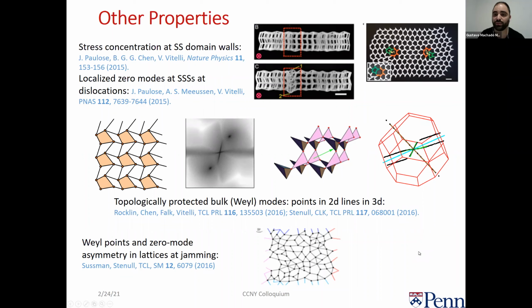Okay, so even though it's not fully, you still have some wiggle because it's not 6 nearest neighbors. Unless you've chosen some particular form that might be sloppy, but it has 5 neighbors per site and it will be stable. Now some of those exotic lattices actually can be quite interesting. They will do funny things. Now we looked at one which was, I've forgotten the details of this one also.